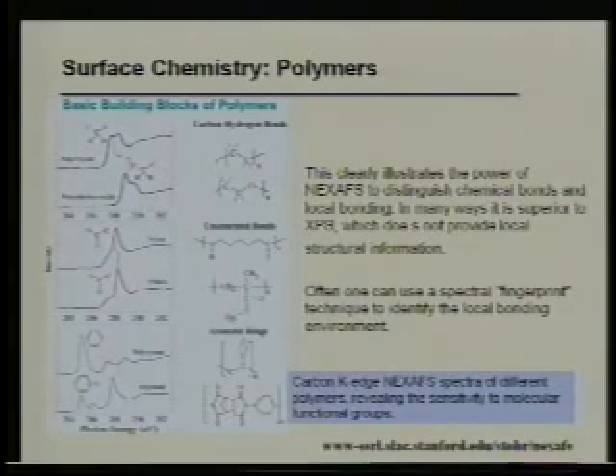The pi star features show, again, you get these sharp features in the near edge. And then if you have sp2 bonded, which you see in the polystyrene and the polyamide, you get a peak again at lower energies. That's related to the pi star exciton, this time in carbon. But the nice thing about this is you get a fingerprint for each material. So if you're searching for a particular material, you can compare it to these fingerprints and actually separate out structures.